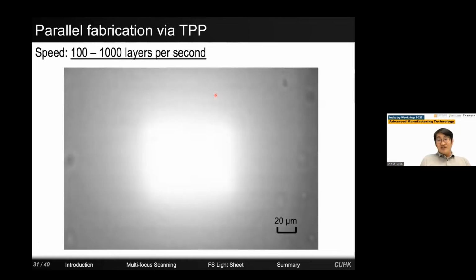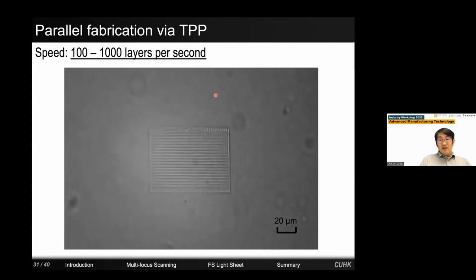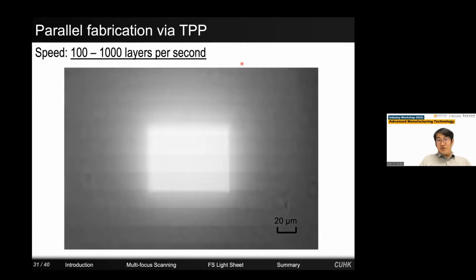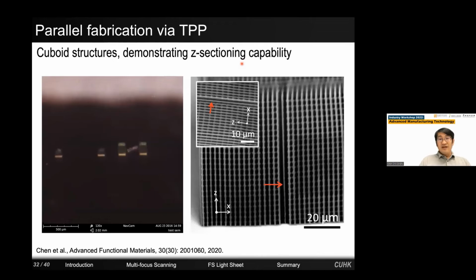So you can see using the system here, each exposure defines a layer, but you're actually seeing a slow motion because every second we can define roughly 100 to 1,000 layers. So this further pushes the fabrication rate of our previous system by 1 order of magnitude. Okay, you take out the printed part, it's transparent in optical microscope, but in electron microscope, you can see fine log pile structures being created. You can also see these artifacts or defects caused by a dead DMD pixel.